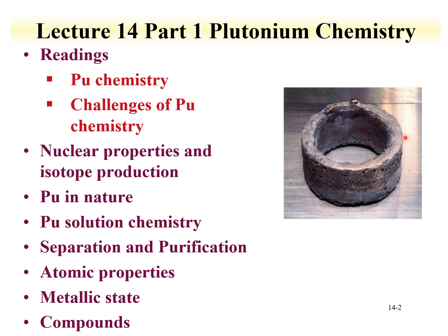And here we see an example of a ring of plutonium. This is made from an electrochemical process where you can form plutonium in a molten salt. The melting point of plutonium for a metal is relatively low. It can drip off the electrodes and form into rings, and there's a reason that they would form this plutonium into rings, and it has to do with criticality safety. If this is plutonium-239, one way of preventing it from undergoing fission is to have a shape which has a very high surface area, so the ring is one way of doing that.